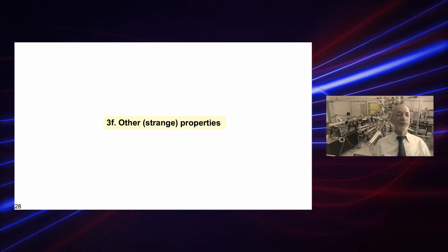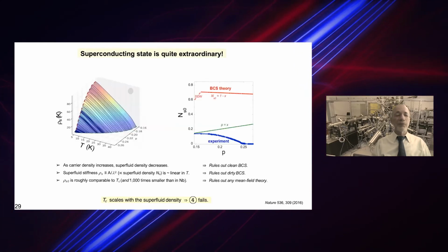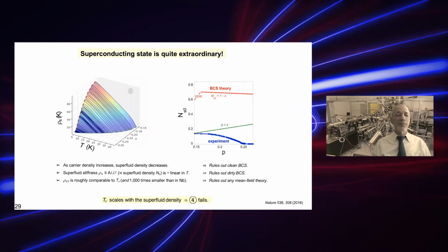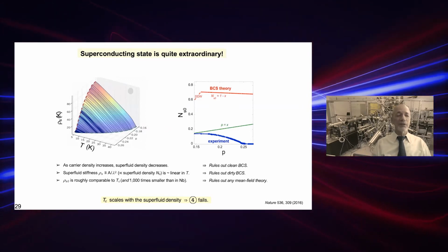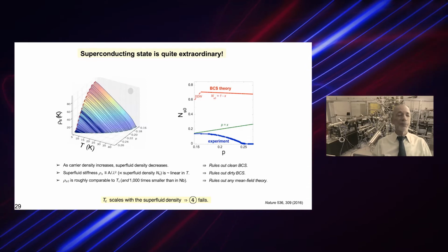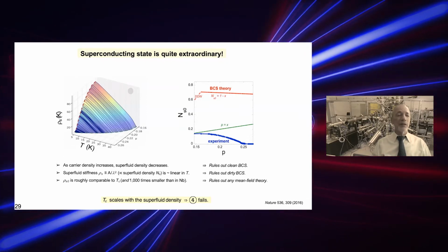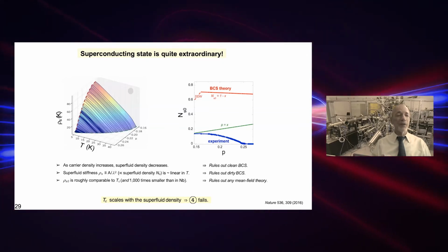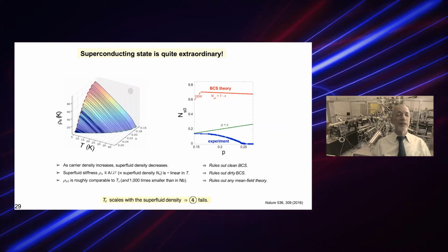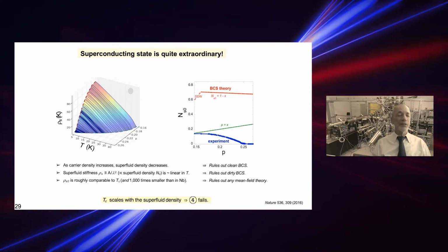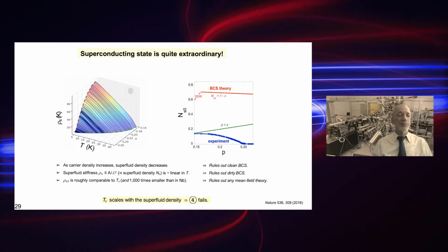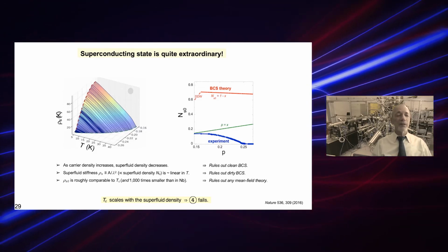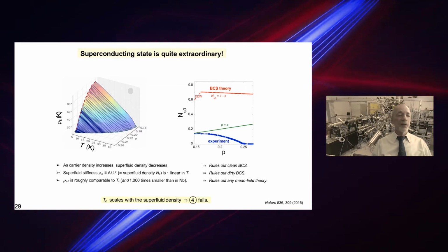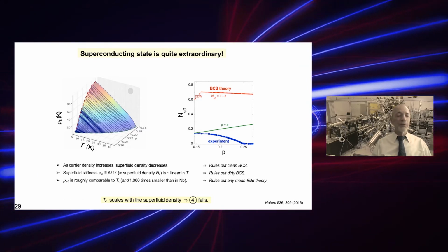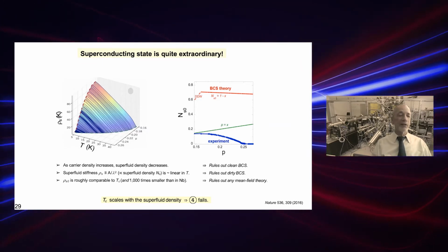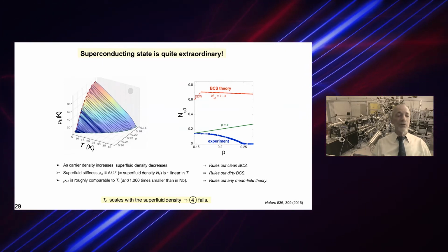Let's look at the other physical properties. We have studied systematically the key parameters of the superconducting state, such as the magnetic penetration depth. This is a plot of the superfluid density as a function of doping and temperature. It brings in several surprises. The first, this superfluid density is basically linear in temperature all the way to TC. This is surprising because in the BCS, the gap should close at TC, and we should expect some leveling close to TC. Second, as we increase the doping, the superfluid density should increase, tracking the carrier density. But what we see is the opposite. It decreases actually all the way to zero.